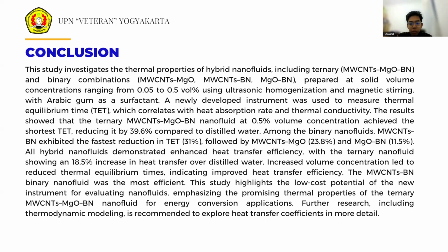Thermal equilibrium time as an indicator of conductivity. The thermal equilibrium time emerged as a crucial metric in the study, demonstrating that nanofluids with higher nanoparticle volume concentration reach thermal equilibrium faster, which indicates better thermal conductivity. The faster a nanofluid reaches equilibrium, the more heat it is able to absorb and transfer in a given time. This aligns with the fundamental principle that fluids with higher thermal conductivity are better suited for heat transfer applications, including those in energy storage systems.